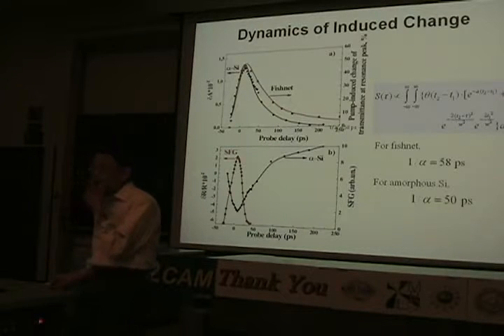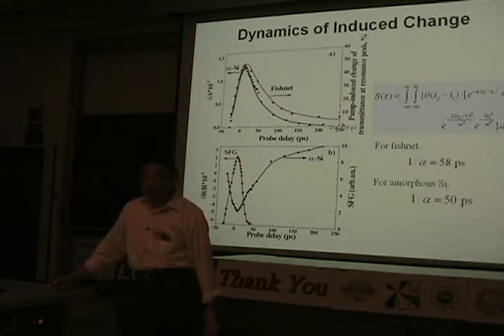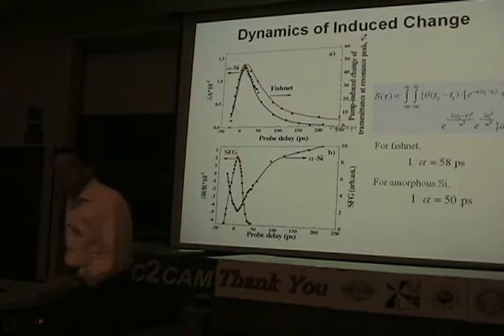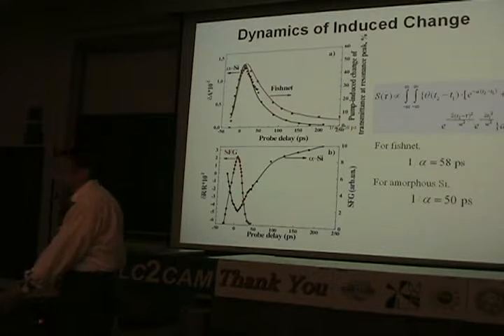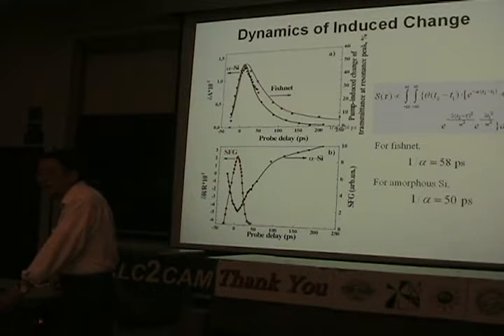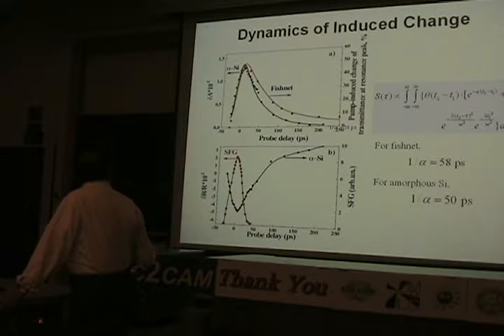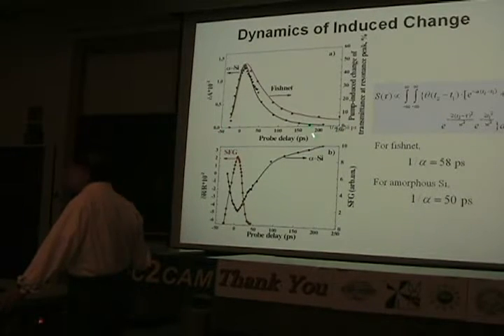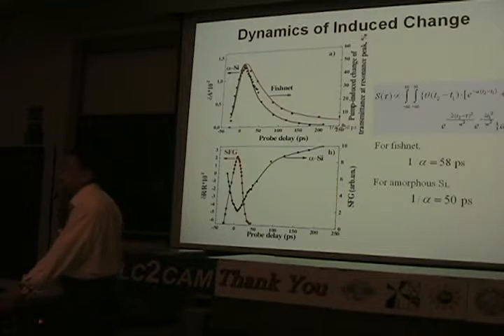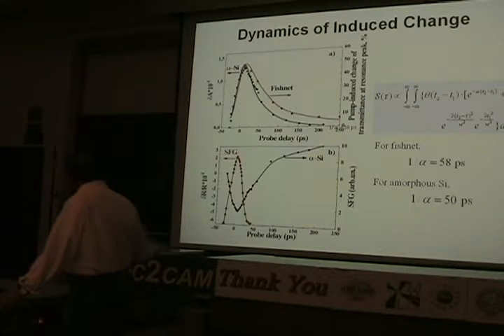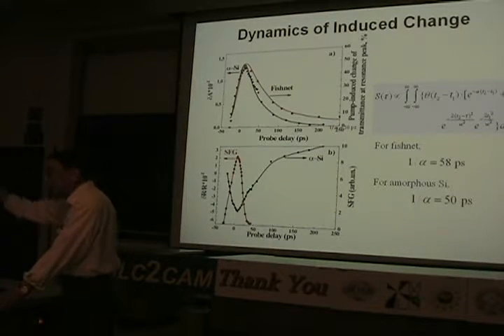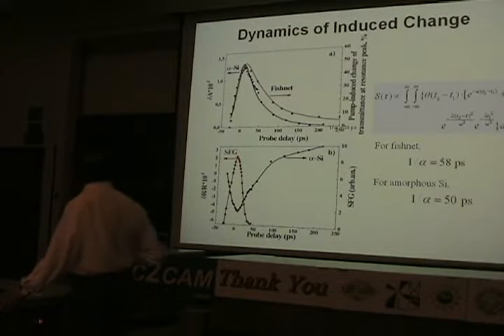So the question is, where does this refractive index change come from? And of course, it's coming from excitation of the amorphous silicon. And here we do the dynamics measurements as a function of the probe delay. You can see that after the excitation, it decays away. And that decay is because of the carrier relaxation in the silicon.